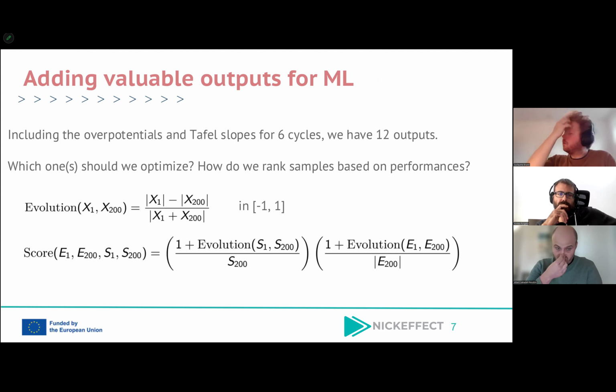For this, we defined two quantities. First, the evolution of, on one hand, the potential and on the other hand the Tafel slope. The evolution is between -1 and 1. -1 meaning that the evolution was very bad, the sample degraded, and +1 meaning that the evolution is positive for the sample. And then we also define the global score for the film.